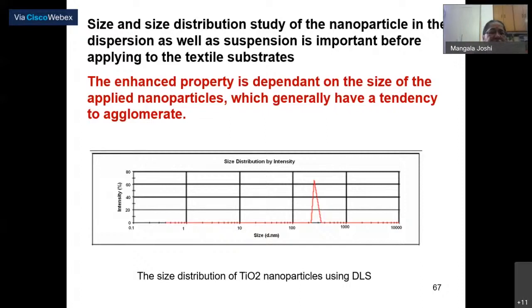This gives not only the size but also the size distribution. As you can see here, on the y-axis is the intensity percentage and on the x-axis is the size in nanometer. So you can see this sample has a particular size, TiO2 nanoparticles. In this peak, you can see that maximum particles are of one size and there is a little particle size distribution. So the enhanced property is dependent on the size of the applied nanoparticles. Obviously there is some kind of agglomeration. If agglomeration is there, then you will get 2-3 peaks. So whenever you are putting the sample on DLS, you have to see that your dispersion is very nice, uniformly distributed, and there are no agglomerations in the sample.